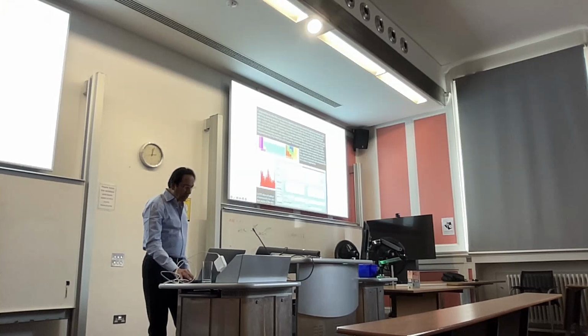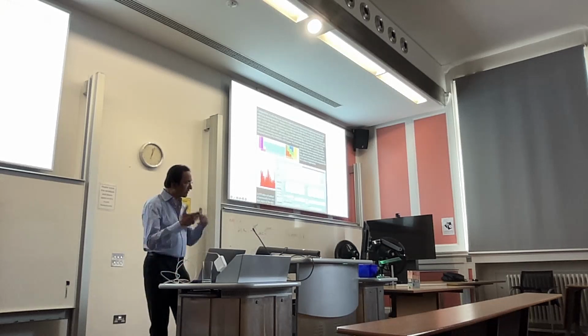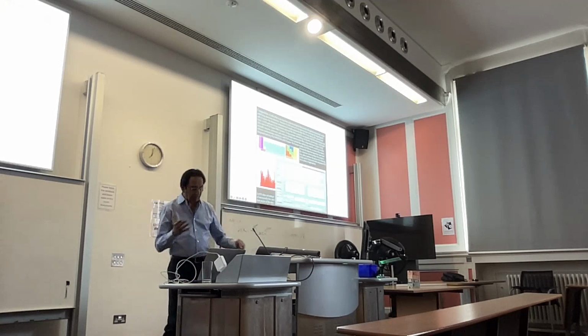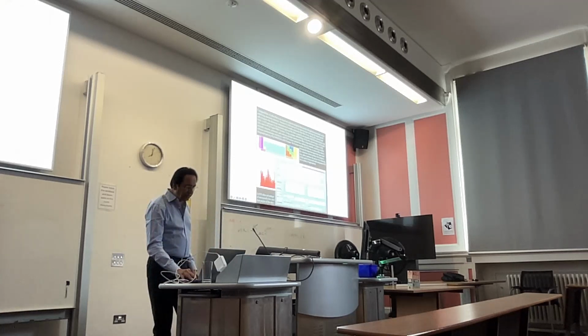Okay. So what we do here is we basically select the elements of interest to us. And then we watch only those elements as a function of the film being grown. You can see there are two different elements that we picked here. They're growing, and you can see the ratio of these elements is changing as the film thickness is increasing. And that's because of this correction factor, because there is a layer that's absorbing above, and you have to correct for it. So what we do is we let this go for a little bit, and then we extrapolate this data asymptotically to the origin. Then that ratio corresponding to zero thickness gives you the correct composition.